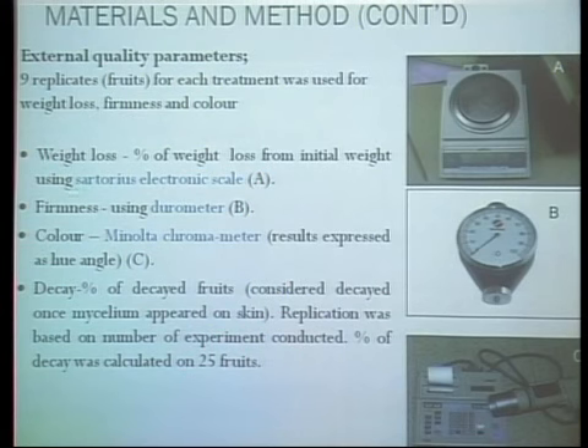Now, the weight loss was measured using the Sartorius electronic scale, and that is it over here, and it was calculated as the percentage weight loss from the initial weight. And then the firmness was measured using the durometer, and that's the durometer. The durometer has no physical unit. The values were arbitrary numbers. So the higher the value, the higher the firmness, and the smaller the value, the lower the firmness of the fruit. And then the color was measured using the Minolta chromameter. Higher values mean higher inhibition of color, and lower values mean the inhibition is very small. We will look at this when I discuss the results.